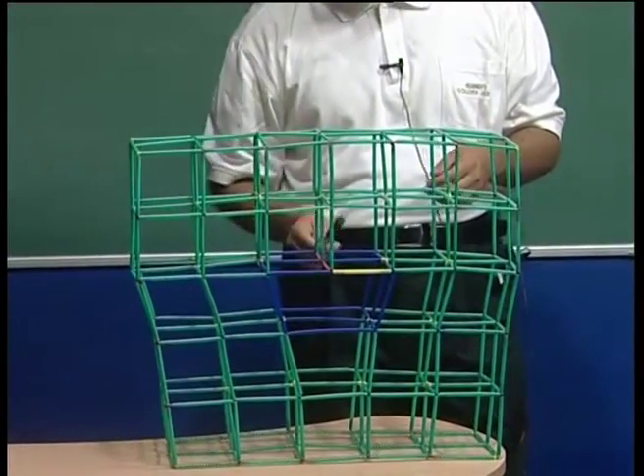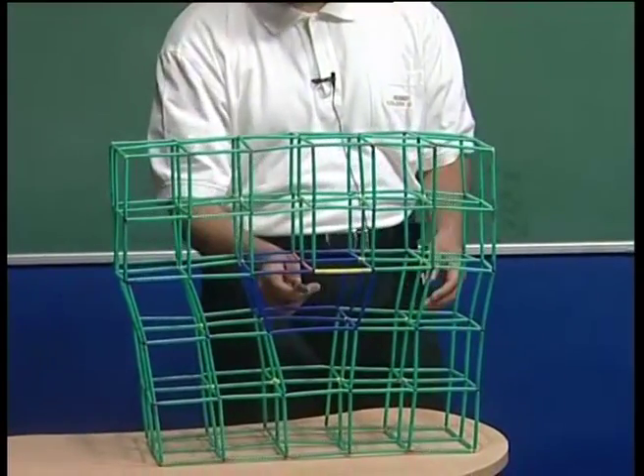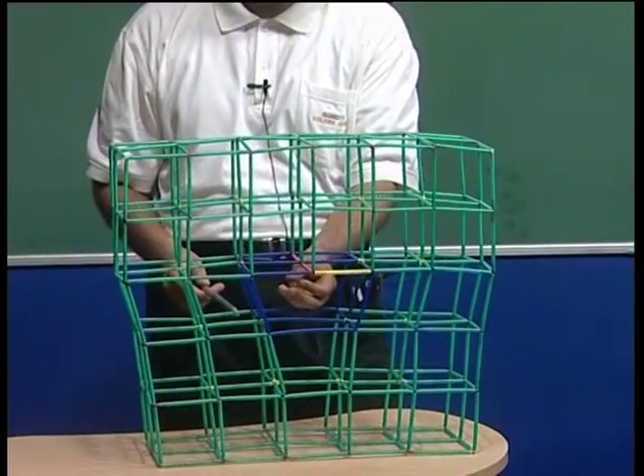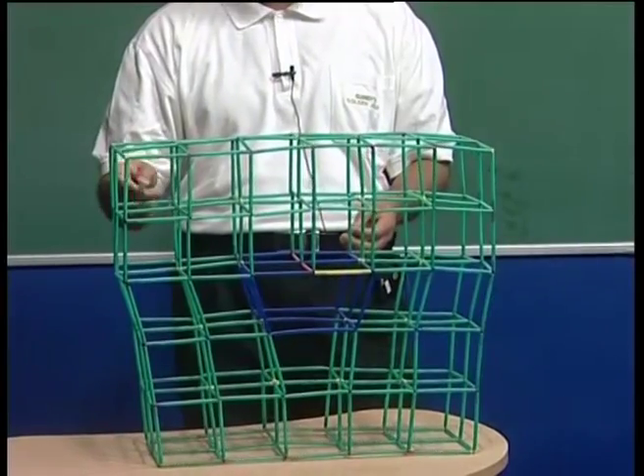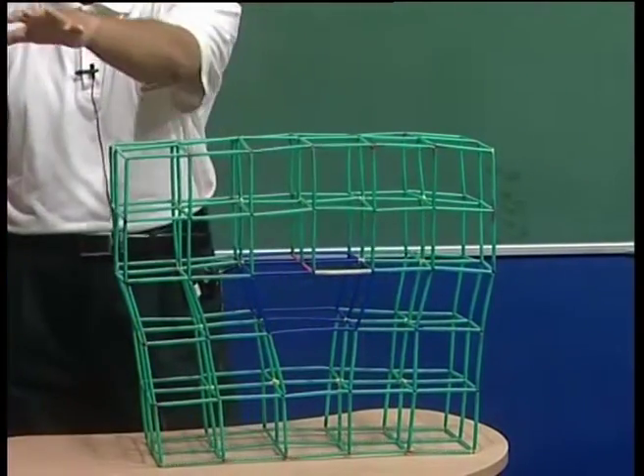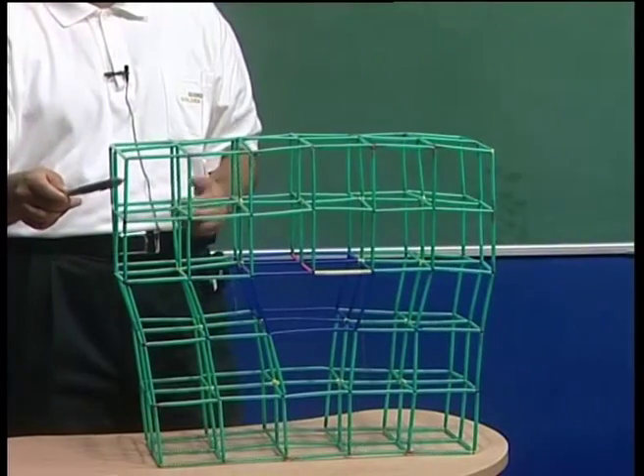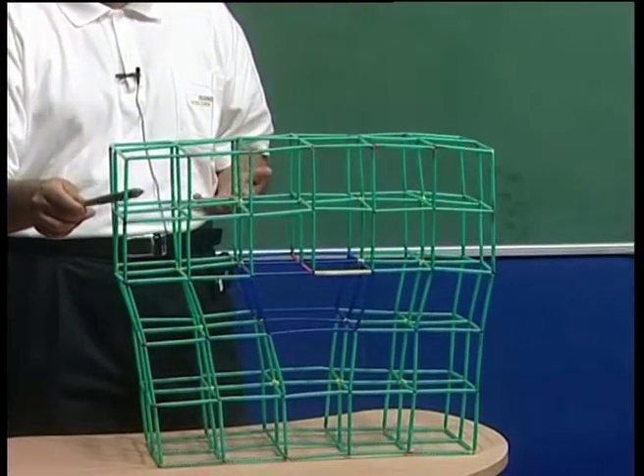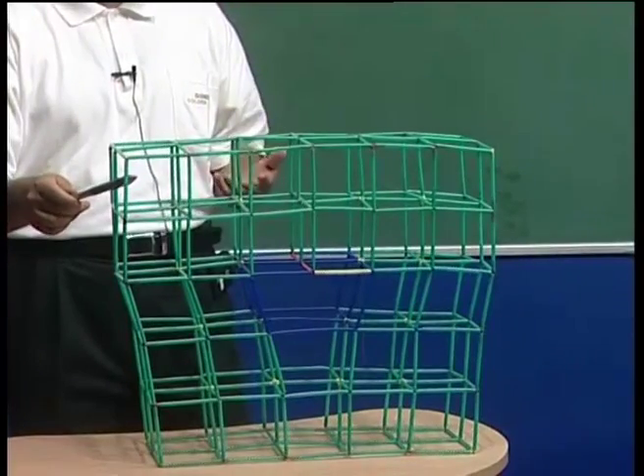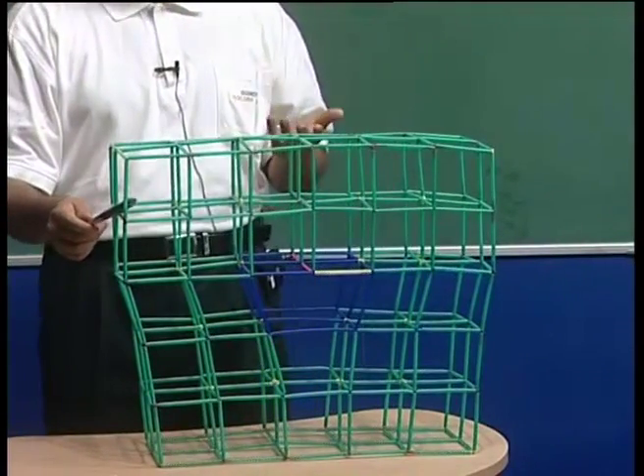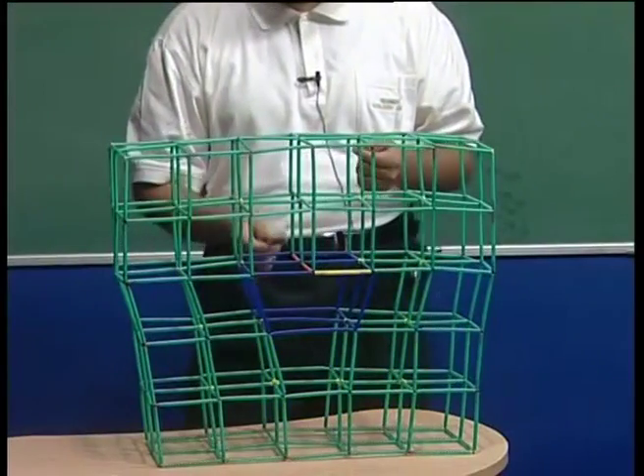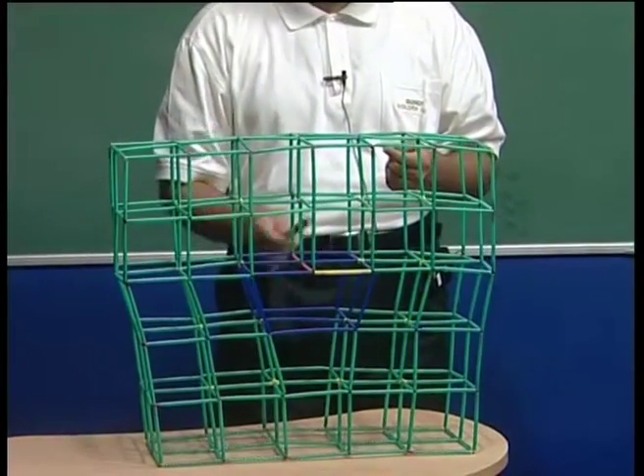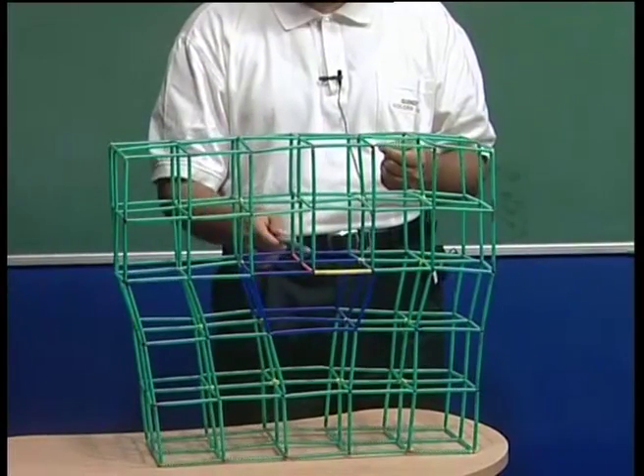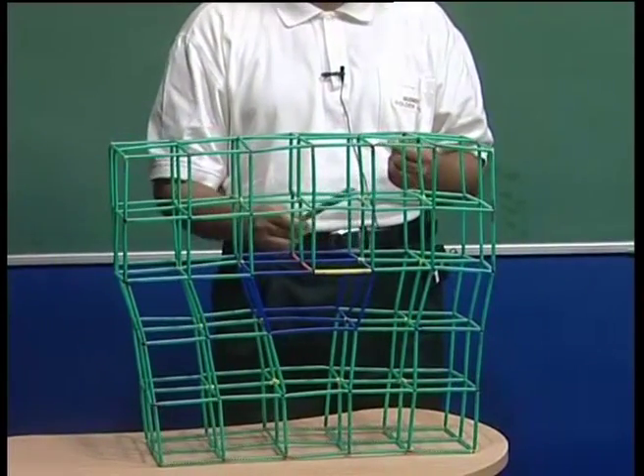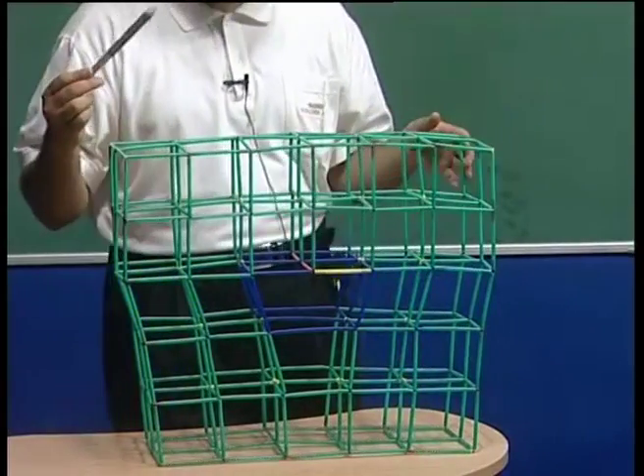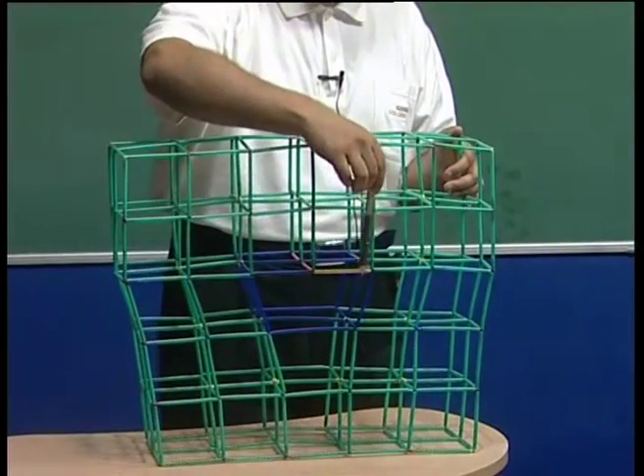Now another thing which you would notice is that the region here is also a region where there is some extra free volume. In other words, as compared to a normal lattice crystal which is far away, which is now a perfect unit cell somewhere far away here, in this perfect unit cell you know the kind of voids which are present, and you know the fraction of those voids. Like for instance, if you take an FCC crystal, you could have octahedral and tetrahedral voids, so we know all about them. But now if you look at this region, there is an extra free volume associated with this dislocation, and this is a very important thing, and we will come back to this, what is the effect of this extra free volume.